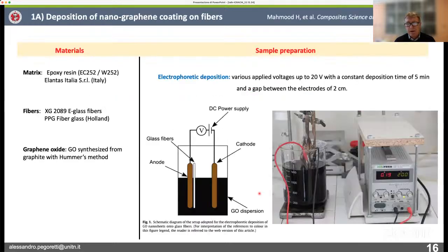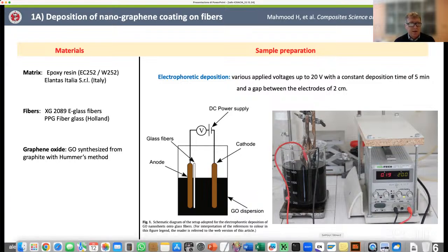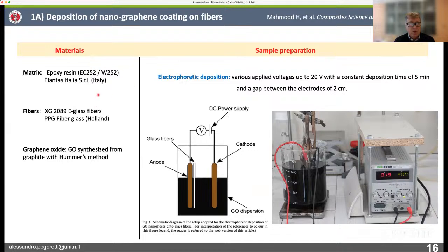And initially we started to work with this technique, which is a relatively simple one. So here in this slide, you can see the type of materials we use. So maybe an epoxy resin. We selected some E-glass fibers. And then also we produce some graphene oxide by using the standard Hummers method, starting from graphite. We disperse graphene oxide in water, basically, in a very mild solution. And at this point, we use electrophoretic deposition to force, basically, the coating of glass fibers with a layer of this graphene oxide. Here you can see the laboratory setup we use for this very simple experiment.